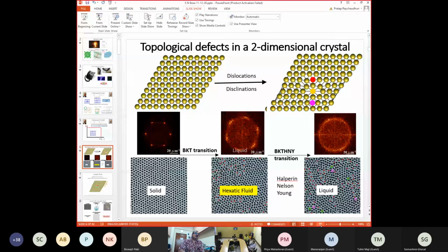So this state at some higher temperature will undergo another Kosterlitz-Thouless transition where you will have this disclination that I am showing here. For example, this red point circled in green or this white point circled in purple, these are the disclinations. And when you have this disclination, your orientational order is completely lost and you have a liquid. So if this is a liquid and this is a solid, what do you have in between? In between what you have is what we know now as a hexatic fluid. It's a strange state of matter which is partially a solid and partially a liquid. It does not have positional order, but it does have orientational order.